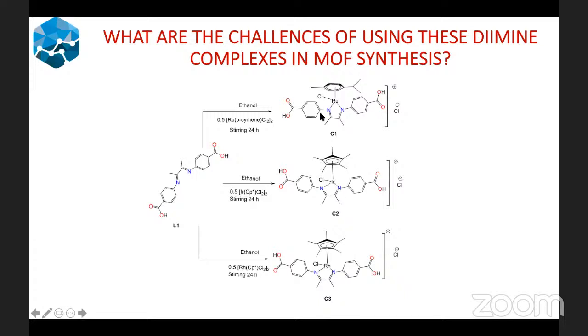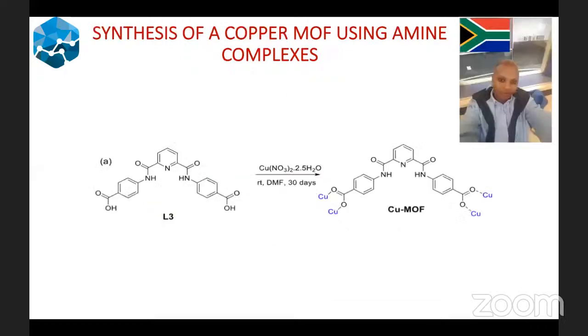What was happening was that during that reaction that we expected to give MOFs, this complex here was undergoing hydrolysis. Remember, this is an imine, so it underwent hydrolysis. So that was the challenge that we faced with these complexes. We were not successful in making metal-organic frameworks using these ligands with catalytically active sites of ruthenium, iridium, and rhodium. So we then shifted our focus from the diimine complexes to amine complexes.